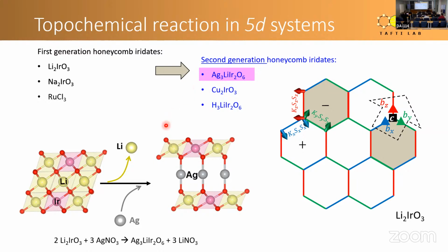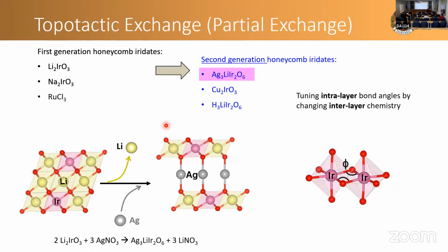But the reason to do this is not just to make a new material. There's actually something deeper that's happening as a result of this exchange reaction. The important thing that's happening as a result of the exchange reaction is a change in the bond angle. Remember that I explained the relative strength of different exchange couplings is determined by the orbital overlap between iridium, oxygen, and iridium orbitals. That very much depends on the bond angle.